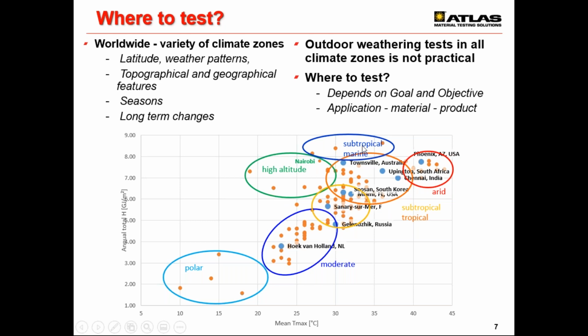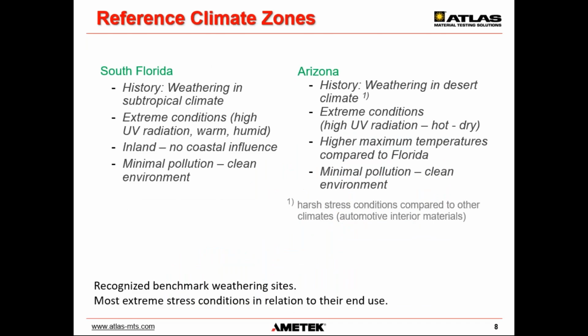But as far as benchmark testing goes, what we really want to do is look at areas that maximize the temperature, which we have here on our x-axis, and also maximize the total amount of radiant energy, which is the value on our y-axis. As you will note, the primary areas where we do a lot of testing are subtropical or desert areas, where we have high temperatures as well as high amounts of UV radiation over the course of the year. That leads us to our reference climate zones, or what we sometimes refer to as benchmark climates. They exist as much as anything for historical reasons, when it was recognized that high UV content and high temperatures tend to accelerate weathering, or at least represent a worst-case scenario compared to cooler, moderate or temperate climates.